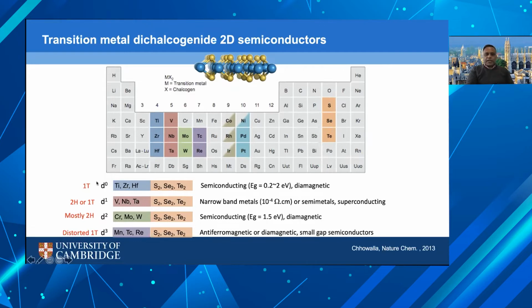What we've been doing over the last decade or so is phase engineering these TMDs. So crystallographically, structurally, they can be in this trigonal prismatic configuration, which is called the 2H phase, or this octahedral configuration, which is called the 1T phase. And so these different phases have different electronic properties. So for example, for MoS2, the 2H phase is semiconducting, and the 1T phase is metallic. And what we've been doing is using chemistry to go between the 2H and the 1T phase, that is between the semiconducting and metallic phase.